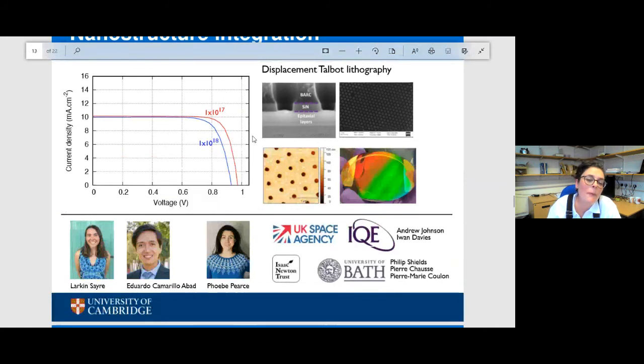So this is comparing our different doping levels. This is a higher doping level, the type of doping that you generally would have with a thicker device. And by reducing down that doping, we can do a lot better in terms of voltage. And we may even consider moving towards a full heterojunction type device rather than a PN junction.